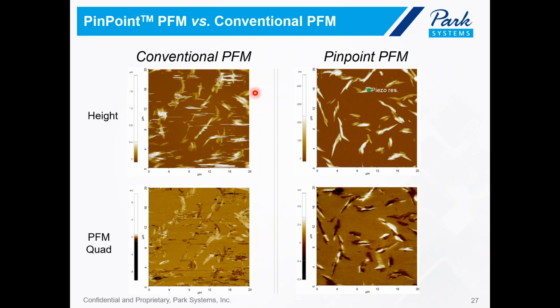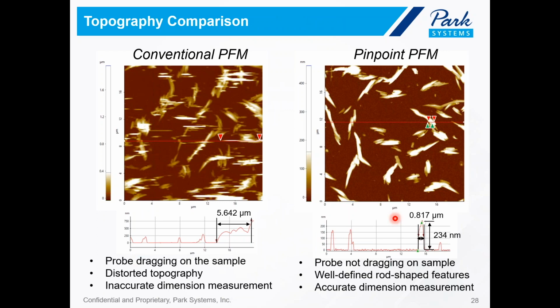So here is an overview of the performance comparison. On the left-hand side, we have the images for conventional PFM, with the height on top and the PFM signal on the bottom. And on the right-hand side, we have the PinPoint PFM, with topography on the top and the PFM signal on the bottom. At first glance, we can tell that the images collected by the PinPoint PFM definitely have better quality compared to those collected by conventional PFM. So let's take a closer look at the topography data.